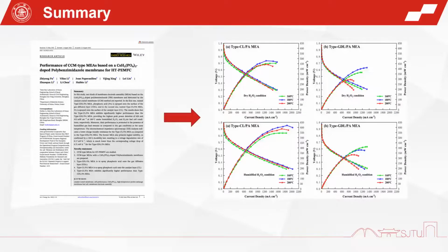In my first author paper, two kinds of MEAs based on the zirconium hydrogen phosphate doped polybenzimidazole membrane and fabricated by the catalyst-coated membrane method are reported. In the first one, named type GDLPA-MEA, phosphoric acid is spread onto the surface of the gas diffusion layer, and in the second one, named type CLPA-MEA, PA is spread onto the surface of the catalyst layer.